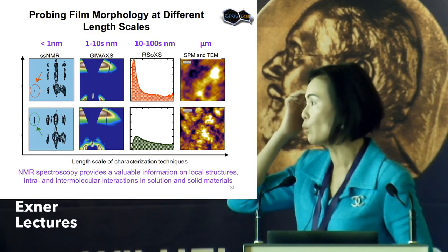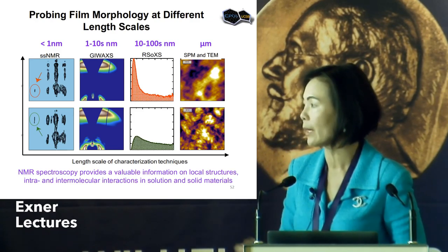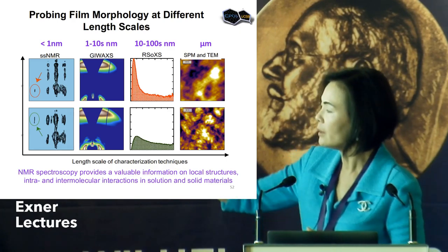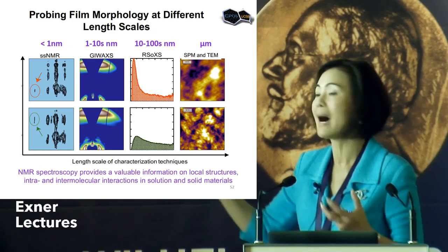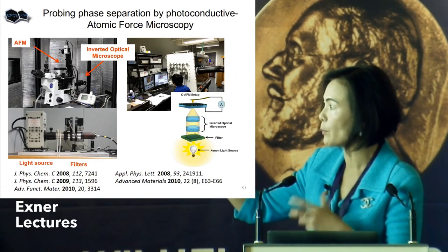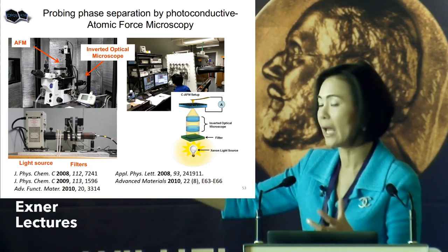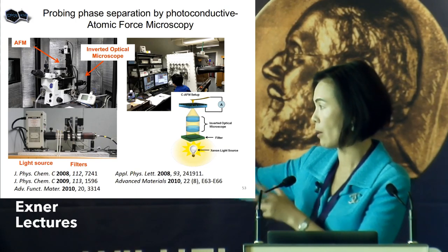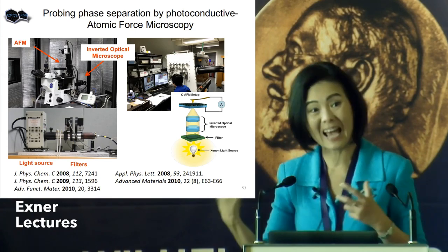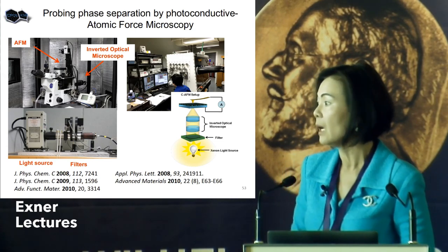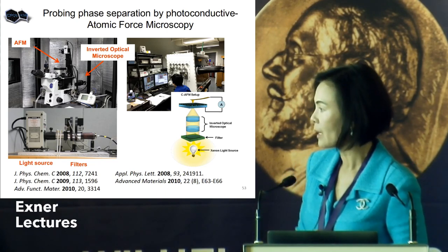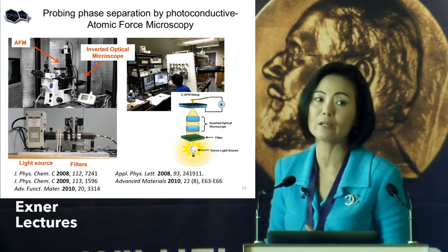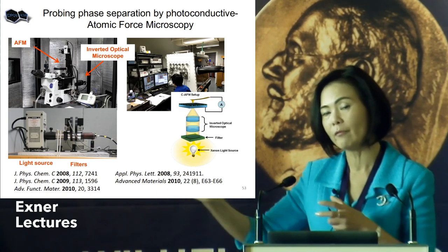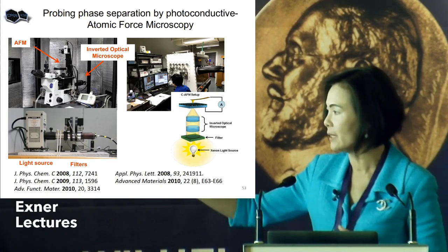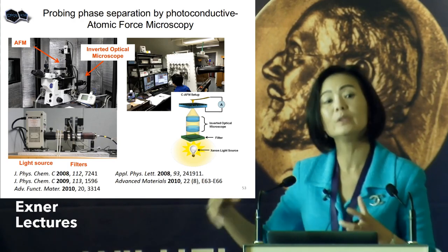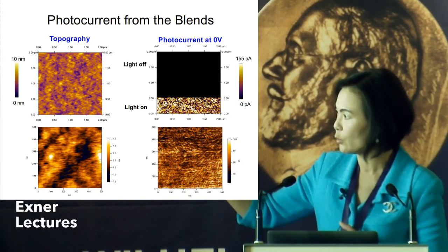And then in our group, we also spent a lot of time to develop scanning probe microscopy and also TEM to probe that. So early on in my career, for this technique, you couldn't buy a commercial instrument. So we bought an inverted optical microscope with the AFM and also a light source and everything. We put it together, and then we also put that whole setup in a custom-made designed glove box, and that allowed us to do nanoscale conductivity measurements simultaneously with the film morphology. And then we can also shine light onto that, and you really measure the nanoscale solar cell properties and correlate features with the morphology. And so we shared the design with two local companies, and so now you actually can buy the setup, but many years later. So here I show you an example of that type of data.